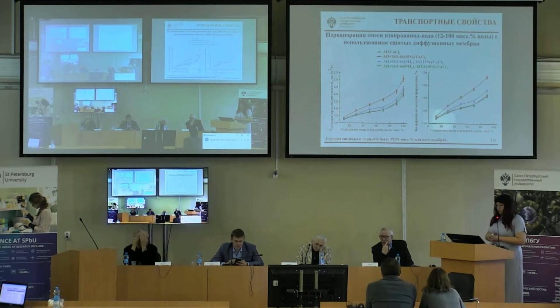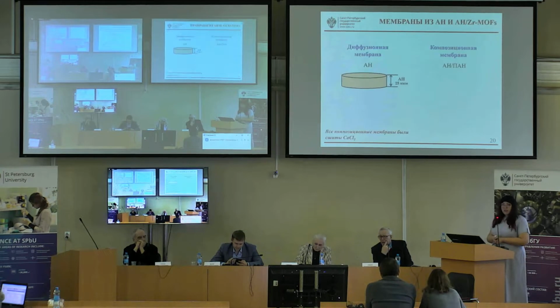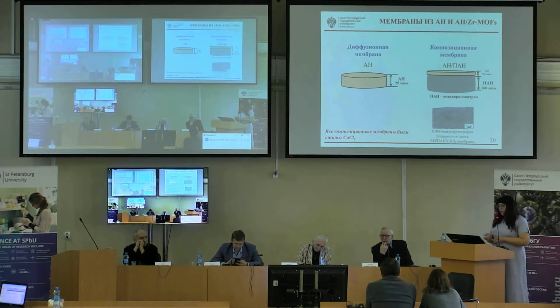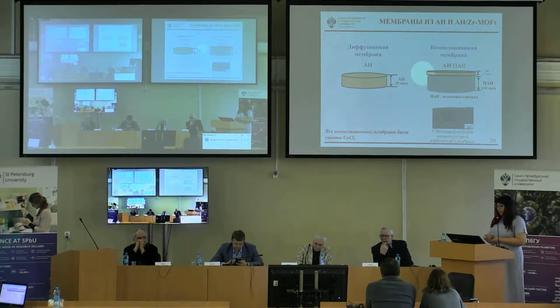Cross-linked unmodified and modified diffusion membranes were tested by pervaporation of an isopropanol-water mixture over a wide range of concentrations. All membranes showed high water content in the permeate. The dependencies of the specific productivity and the concentration factor on the water content in the initial mixture demonstrate an increase in these parameters with an increase in the water content in the initial mixture.